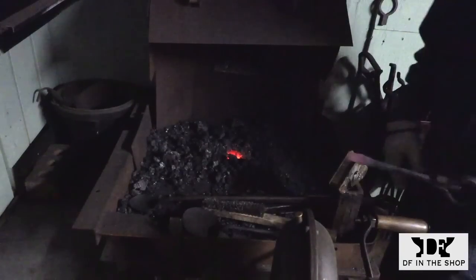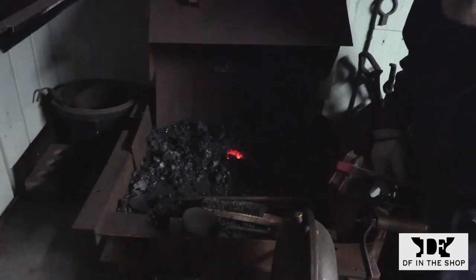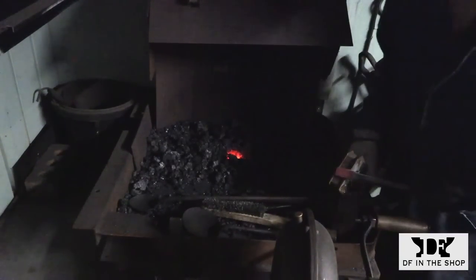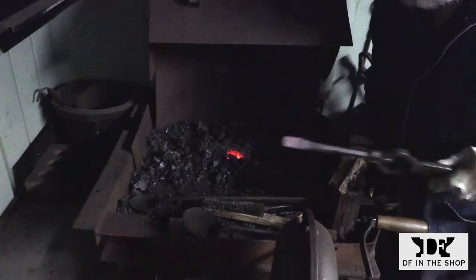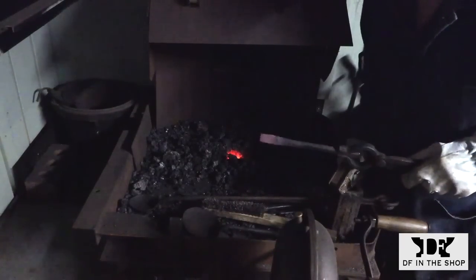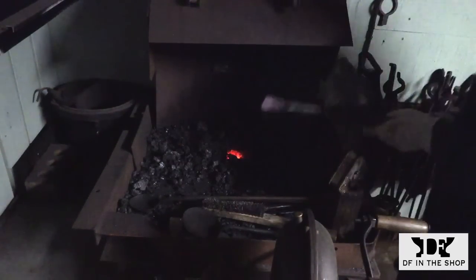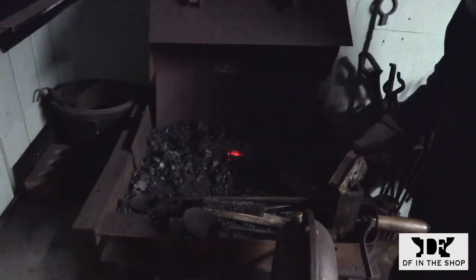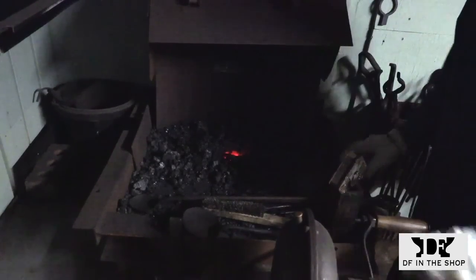So at this point, I've turned off pretty much all the lights in the shop, and I've let the bar cool down quite a bit. And you can see, even in a dark shop, this is a barely visible dull red. And there's a little bit of magnetism. It's losing its magnetism, but there's still some stickiness there. So this is just below the critical temperature, and it's barely visible in a dark shop. If I had the lights on that I had before, this would not even show up as a color at all.